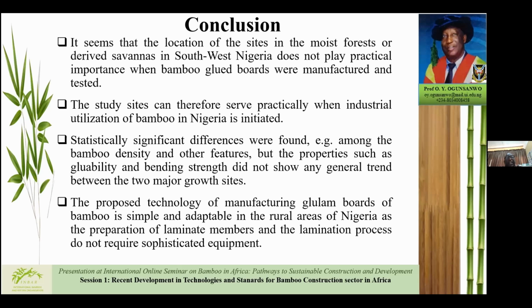So from our findings, in conclusion, it seems that the location, because we have taken bamboo from different locations, did not play any practical importance when the bamboo glue boards were manufactured. And the implication of this is that we have a wide area to collect bamboo in terms of utilization, in the eventual case that the cottage industry of bamboo is established in the study area.